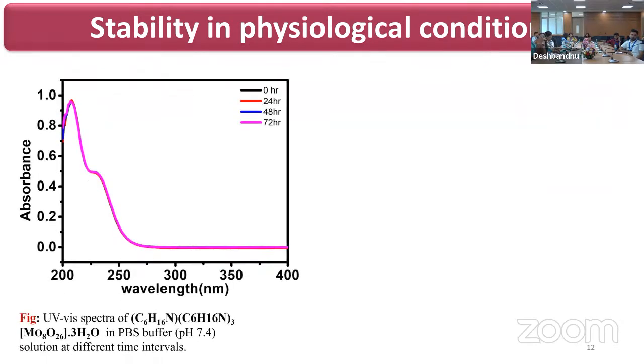So for that, we checked the UV-visible spectroscopy of our solid in PBS buffer at pH 7.4. And we observed that after 72 hours, there was no disappearance of peaks, no appearance of new peaks, and no peak shift, which indicates that the structural integrity of our synthesized form is maintained till 72 hours, which is a criterion for any material to be used for biomedical applications.